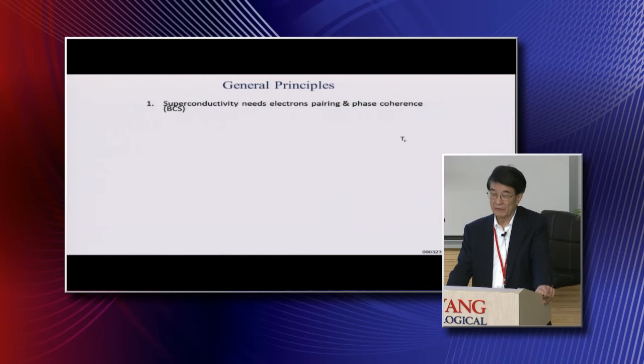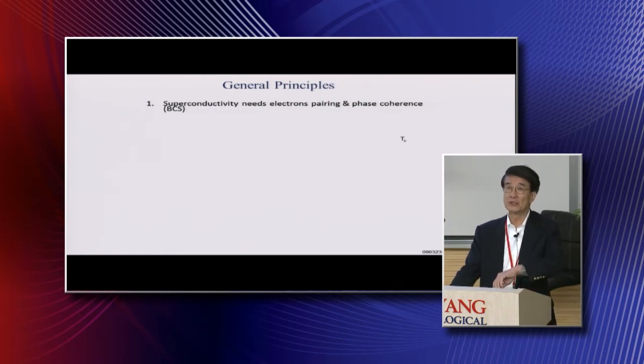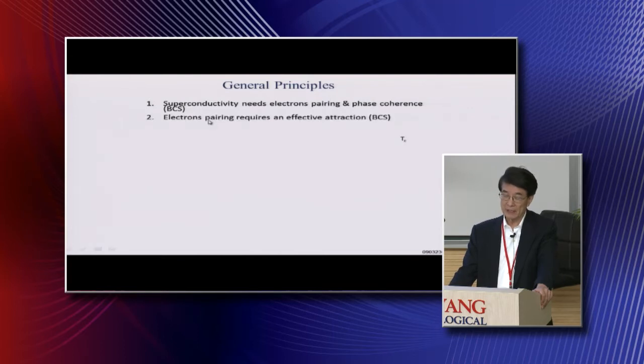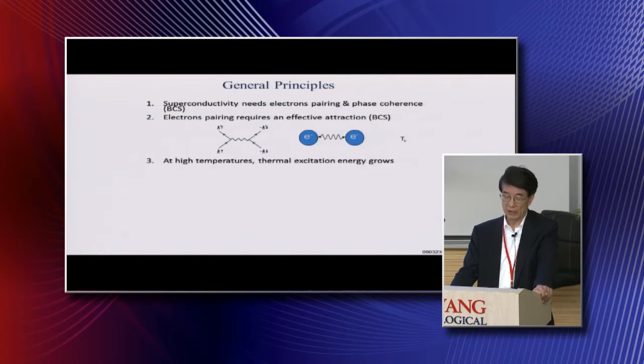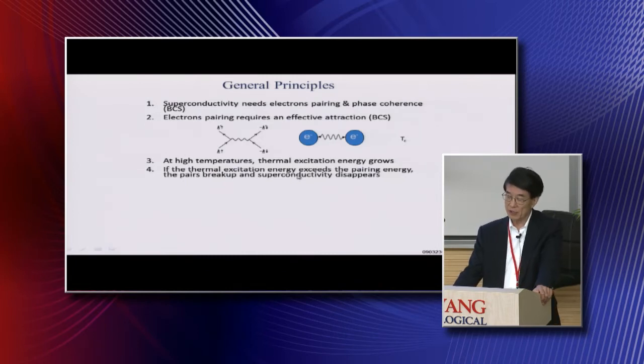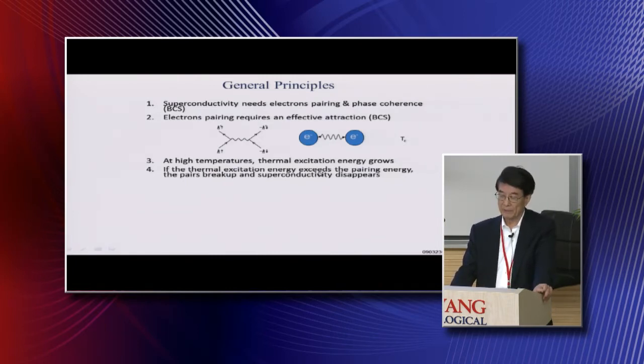The general principle for superconductivity to occur, as I already mentioned, is that it needs electron pairing, and the second thing is phase coherence, as described in the BCS theory. The electron pairing requires an effective attraction between them, and the mechanism is the exchange of phonons. At higher temperature, the thermal fluctuation increases, and if the thermal excitation energy exceeds the pairing energy, the pairs break up and superconductivity disappears.